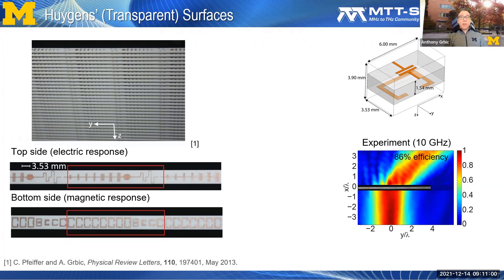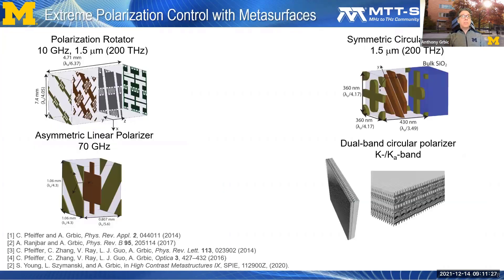As can be seen in the photograph, capacitively and inductively loaded traces are used to realize electric dipoles, and capacitively loaded loops to realize magnetic dipoles. By properly designing these electric and magnetic dipoles, we showed that it's possible to redirect a normally incident beam, for example, to an angle of 45 degrees with high efficiencies at microwave frequencies with only a single layer of inclusions. Instead of loops and rods, one can also stack patterned metallic claddings to achieve the same effect and field control.